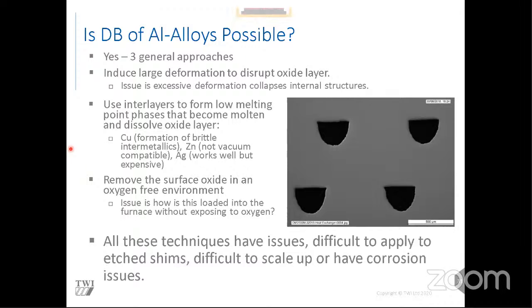So the third approach is to remove the surface oxide in an oxygen-free environment, which in itself is not too difficult - there are many different processes for removing oxide. But the issue is, how do you load this into the furnace without exposing it to oxygen? The problem with aluminium is the oxide layer will grow in less than a second - not to full thickness, but a significant enough layer forms in a second. So it might take you 10 minutes to load into the furnace, and you're going to have oxide present. So all of these techniques have issues - they're either difficult to apply, difficult to scale up, or there's corrosion issues with the interlayers.